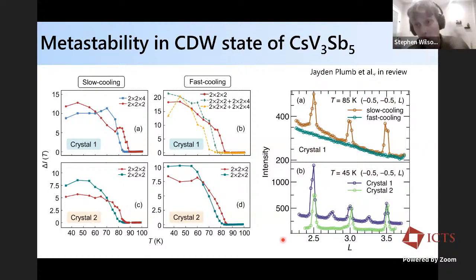If we just look now again at the whole crystal at once and just diffract from it with X-rays, you can take a look at how these charge correlations evolve as a function of fast cooling versus slow cooling through the charge density wave state. And so if you focus here on crystal 1, all I want to show you is that when you cool through the transition quickly, so you quench it, then you suppress the ordering transition, and you mix the clusters of pixels which turn on at the same temperature between both 2x2x2 and 2x2x4 phases, okay? Whereas in the slow cooling or annealed phase, you don't have that strong mixing. They have distinct onset temperatures.